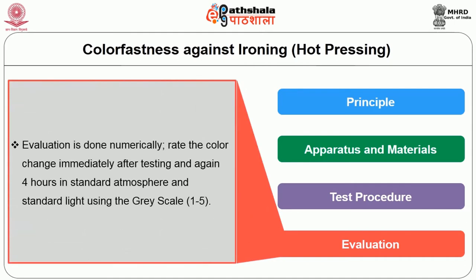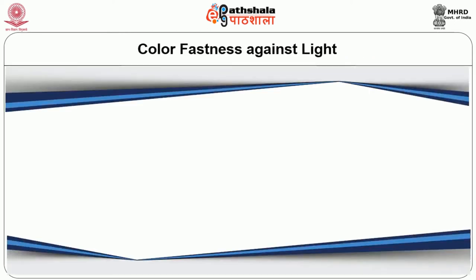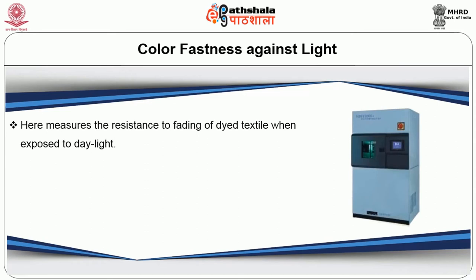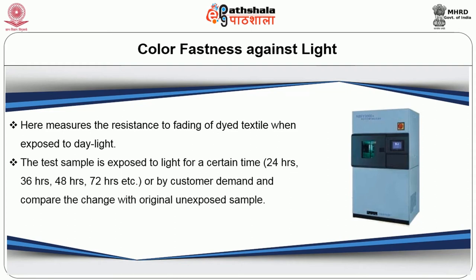Color change rate is assessed immediately after testing and even after 4 hours in standard atmosphere, then graded by grayscale 1 to 5. Color fastness against light. In this test method, the resistance to fading of dyed textiles when exposed to daylight is evaluated. The test sample is exposed to light for a certain time, like 24 hours, 36 hours, 48 hours, even 72 hours, as the customer demands, and the change is compared with the original unexposed sample. It is graded using grey scale in the range 1 to 5.